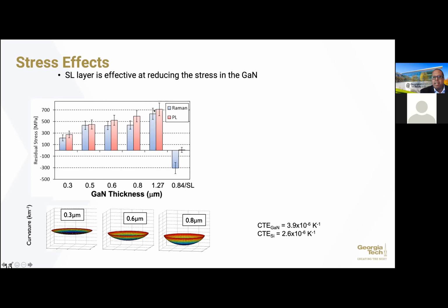But nonetheless, what you see here is that you start having these very, very large stresses. When I use the superlattice structure, what's interesting is that it goes compressive, but right here at the surface, it's close to zero. So there's a lot of things that you can do to manipulate the stresses in the gallium nitride to make this work in the trade-off for increased thermal resistance.